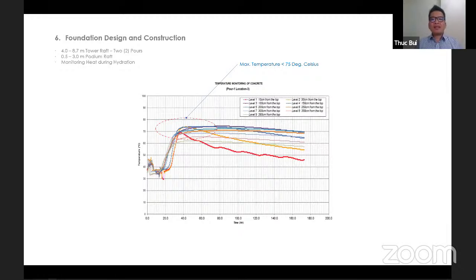We also monitor the heat in concrete during curing, because when the internal concrete temperature is high, there is an increased potential of delayed ettringite formation, which is a material-related issue that can lead to severe cracking. To avoid this, usually we keep the maximum internal temperature of concrete at 80 degrees Celsius. So if you look at the chart here, even though the raft is 4 meters thick, the maximum temperature is just around 75 degrees, which is good.